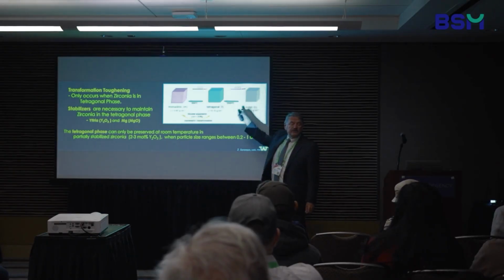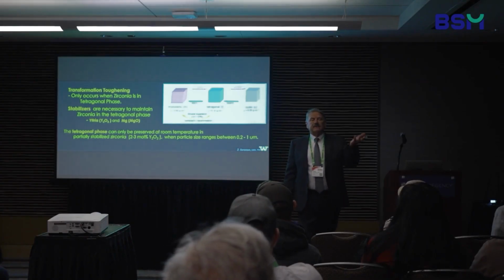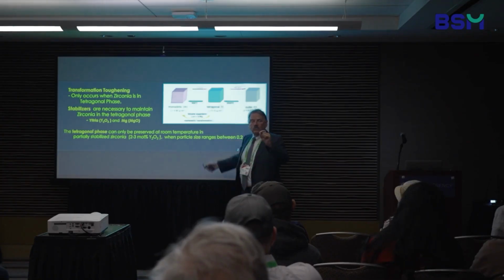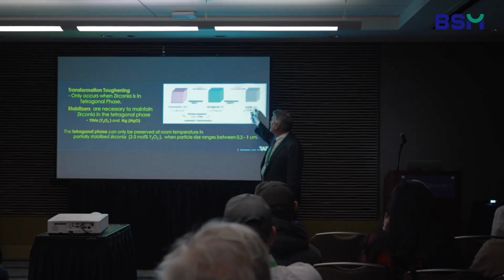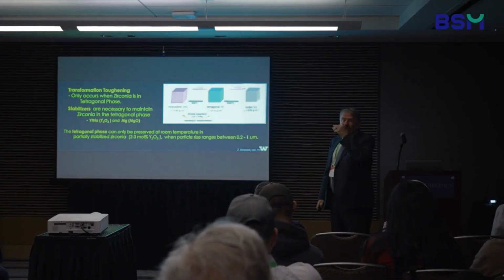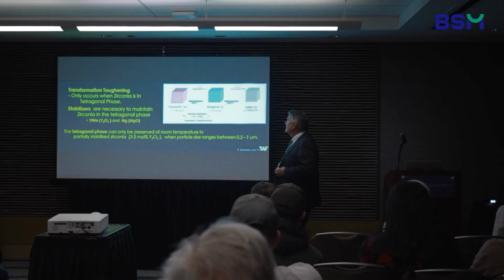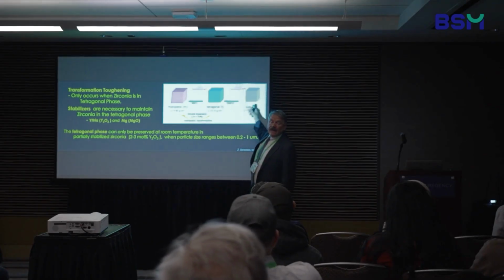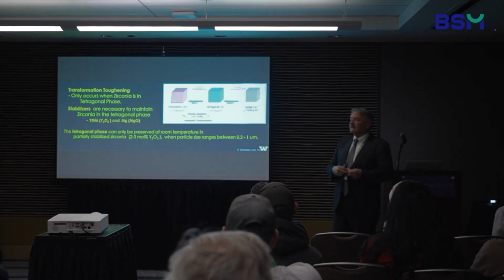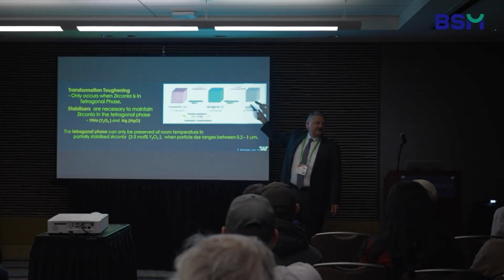So if you want to make it more translucent though, what we do then is we add some cubic zirconia to that, and we do that by increasing the yttria content. So standard high strength is a 3Y, then we can do a 4Y, which is 25% cubic zirconia, or we add 5Y material increase in that, and we then get a 50% cubic zirconia, and now you'll end up with something that's as translucent as medium translucency Emax material. So the problem is once I get up here, I have 50% cubic zirconia, I no longer have that transformation toughening phenomena. Now, if I have 600, 700, 800 megapascals, no problem for single crowns and probably okay for a 3-unit bridge.